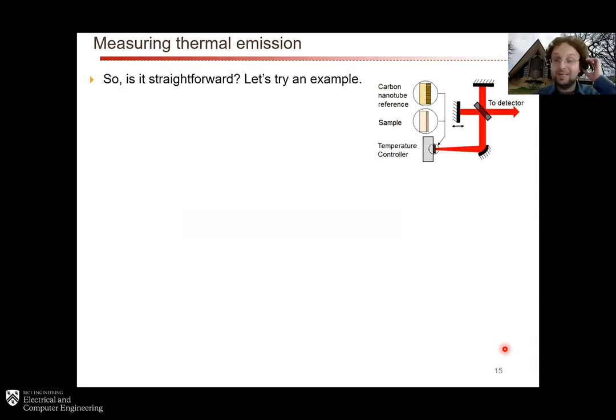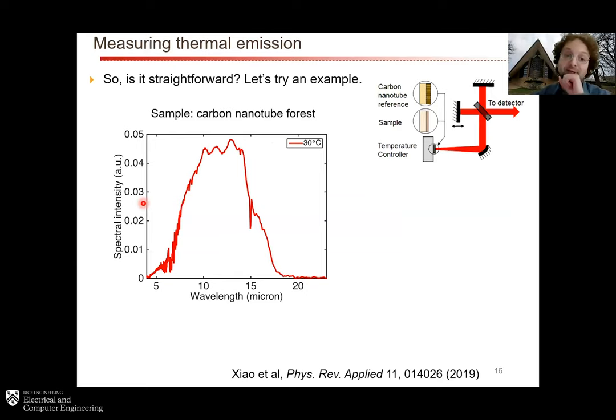So let me show you an example of this, something that we found very, very strange when we first started doing these measurements some years ago, and we finally resolved over the last couple of years, and we know what's going on now, but let me show you. So here's a very, very simple example. This is the spectral intensity. It's in arbitrary units because we are not normalizing to anything. We're not using a reference or anything. So spectral intensity as a function of wavelength for a particular temperature of a carbon nanotube forest, which is about as close as you can get to a laboratory blackbody.